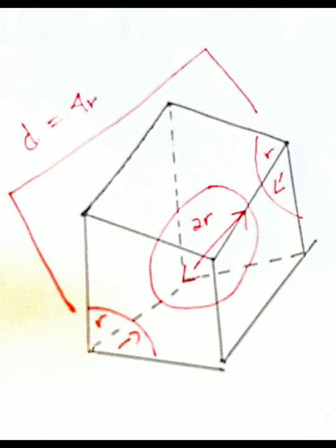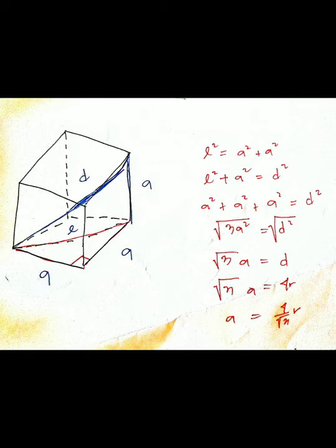After that, we will find the volume of 2 atoms, which is 2 atoms multiplied by 4/3 pi r cubed, equal to 8/3 pi r cubed. Next, we will find the edge length of the cube. So, here's a sphere at the bottom edge of a cube, and a sphere at the top edge. This sphere is twice the radius, which is the diameter, and this is r. Also, this is r. So, the distance between the bottom and top edge of a cube is 4r.